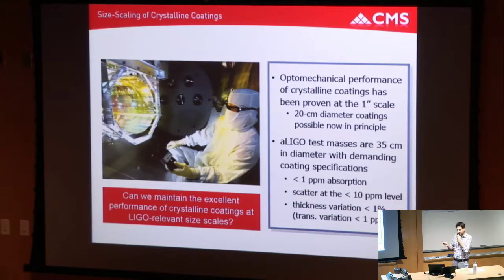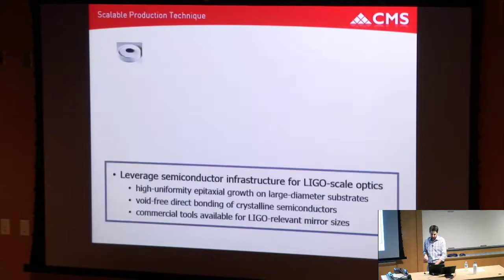Another group of interest is LIGO. Can we do ultra-low Brownian noise large optics? Size scaling is really challenging here, right? They have 35-centimeter optics. I keep showing little 1-inch optics. That optic is bigger than that person's head, not like his eyeball. So we've proven this very nice optomechanical performance at the inch scale, but can we scale up to this large? And we have to maintain sub-PPM absorption, low scatter, and high uniformity.